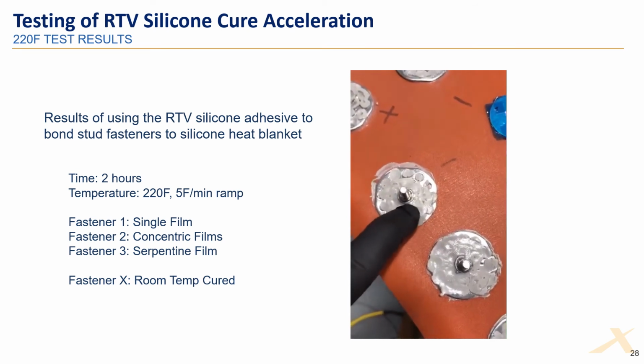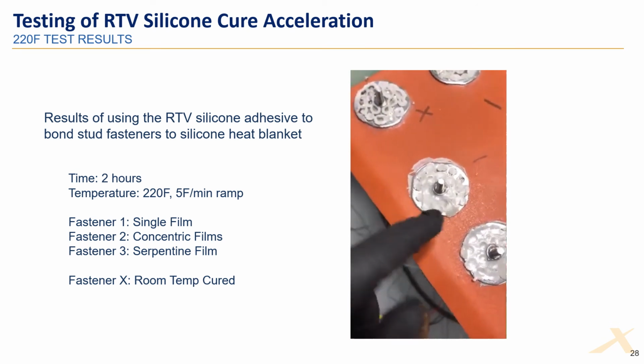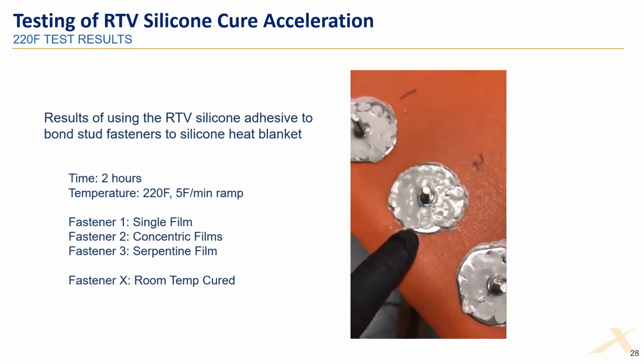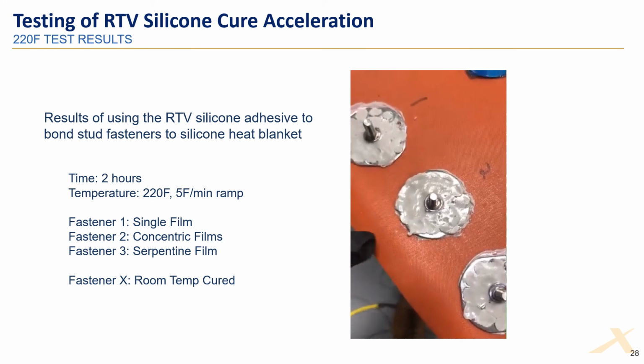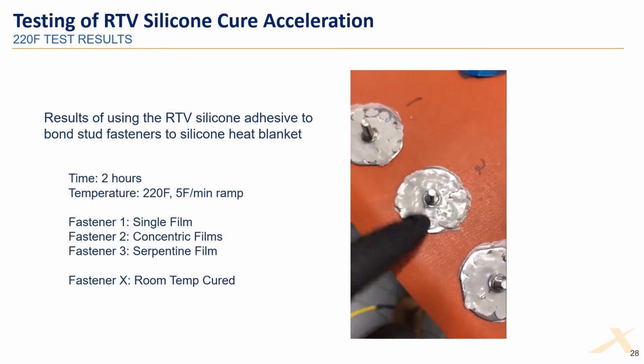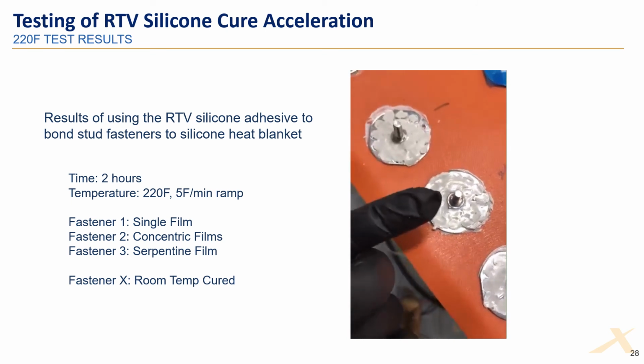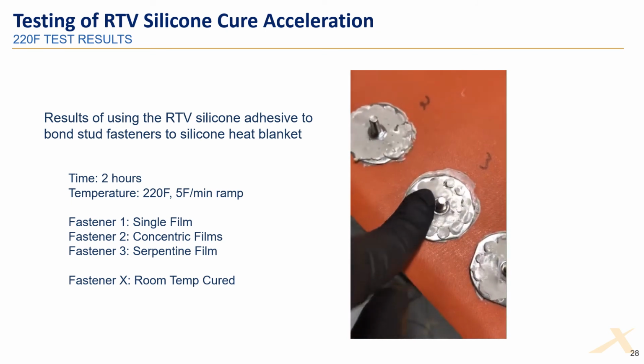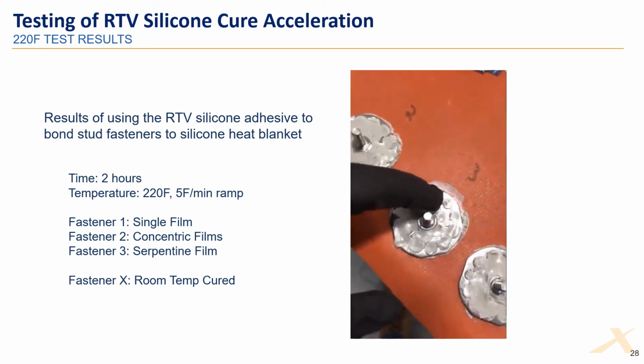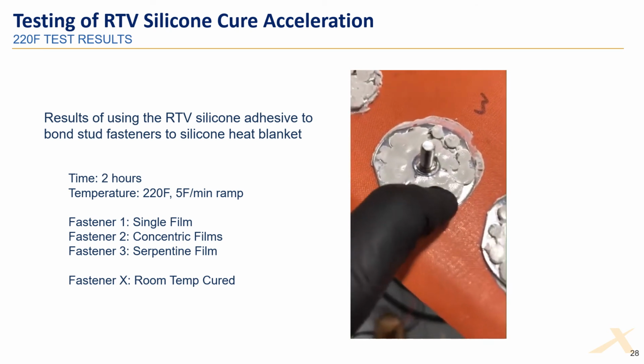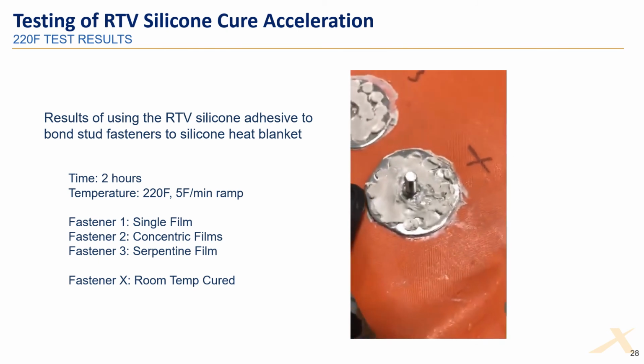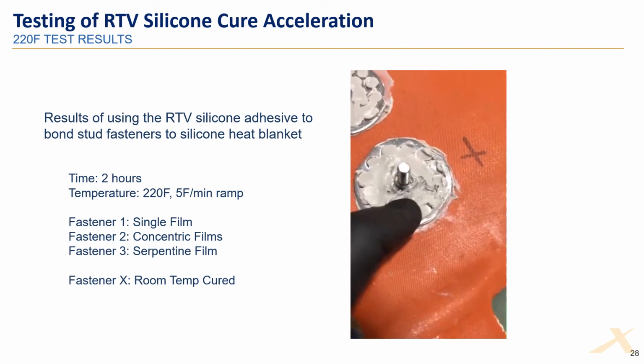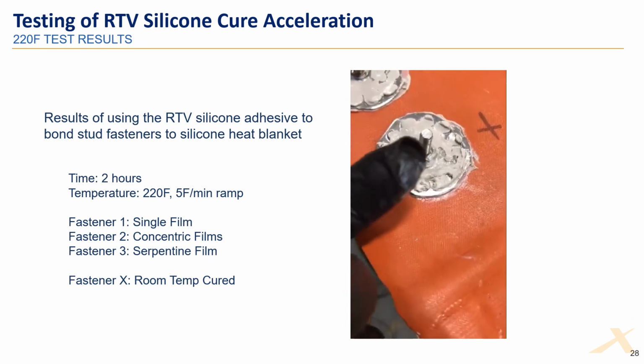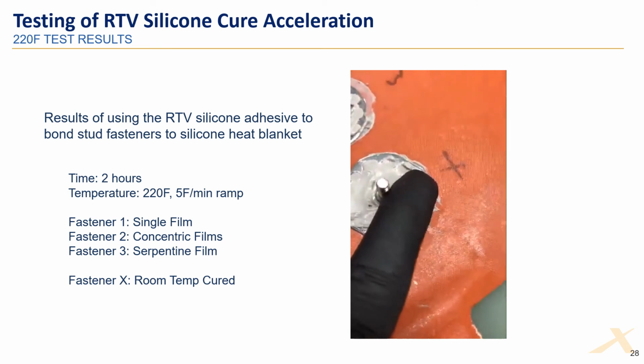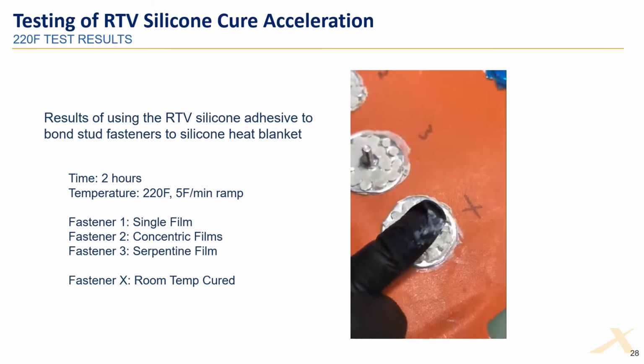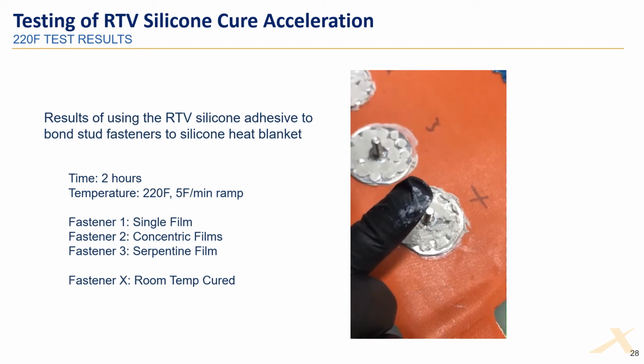So here, the first one is the first design, the single film. The technician here is showing that the adhesive is no longer tacky or sticky, that it is indeed fully cured. Second image there is a concentric film. The third being shown here is the serpentine film design. Fully cured, no tack. There, the X is the room temp cure baseline. You can see it's very soft, unsurprisingly, still gummy. Of course, this is a 24-hour cure system, so this is exactly what was anticipated.